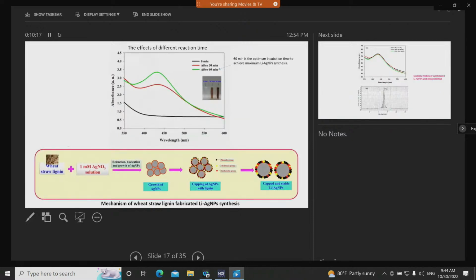Under these optimized conditions, the effect of different reaction times was studied. It was observed that 60 minutes is the optimum incubation time to achieve the maximum lignin silver nanoparticle synthesis. As we can see, a strong absorption band at about 432 nanometers indicates the synthesis of the silver nanoparticles.